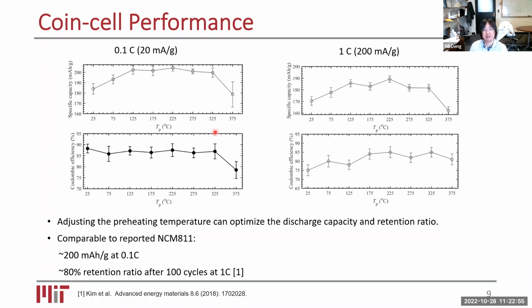So we characterize the specific capacity of the battery, the efficiency for the charge and discharge, and we can charge them also at different rates, how long it would take. So in the battery community, when we talk about the C rate, it is how fast we charge things. So 1 C rate is the rate at which you fully charge a battery in 1 hour. So 0.1 C means that you need 10 hours to charge it. Normally people utilize a low charge rate to characterize the total capacity of the material and measure the performance at different C rates and try to get the retention ratio after like 100 cycles or so.